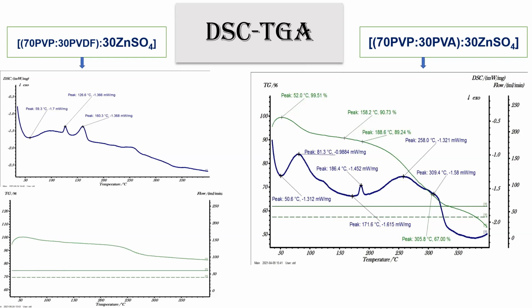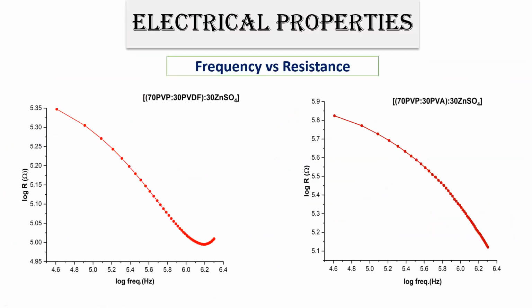Similarly, the TGA data, which shows the weight loss with increasing temperature, also shows improvement in the case of PVDF. Again, the reason is that the semi-crystalline nature is very dominant. So it definitely plays a role.